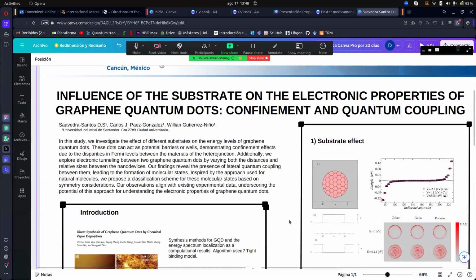These dots can act as a potential barrier or wells, demonstrating confinement effects due to disparity in Fermi levels between the materials on the heterojunctions. Additionally, we explored electronic tunneling between two graphene quantum dots by varying both the distance and the relative size between the nanodevices. Our findings revealed the presence of lateral quantum coupling between them, leading to the formation of molecular states.